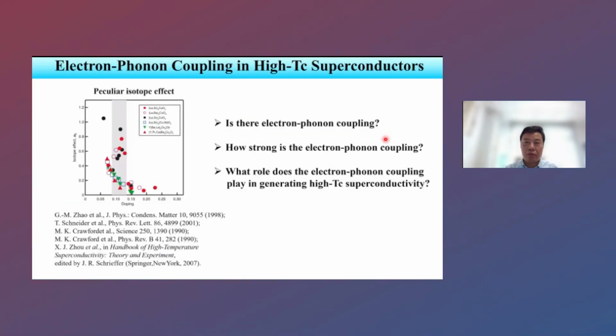And for a long time, people usually neglected the electron-phonon coupling for several reasons. First, some people say electron-phonon coupling cannot produce such a high Tc, it cannot produce d-wave superconductivity, and also from the isotope effect: at optimum doping, the isotope effect is nearly zero. It's the weakest. But I think it's still too early to fully neglect the electron-phonon coupling in cuprate superconductors, and